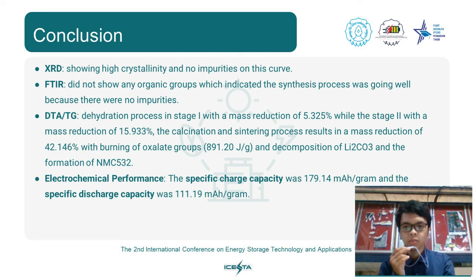The calcination and the sintering process results in a mass reduction of around 42%, with burning of oxalate groups releasing energy of around 891 joules per gram, and the decomposition of lithium carbonate and the formation of NMC532 material. And then for the electrochemical performance, the specific charge capacity was 179.14 milliampere hours per gram, and the specific discharge capacity was 111 milliampere hours per gram.